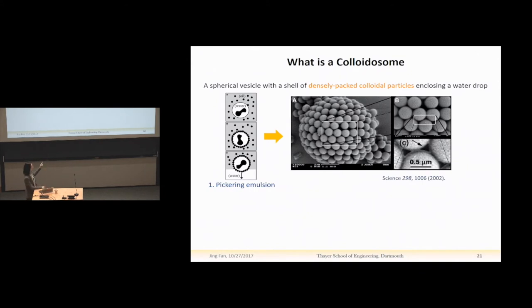But the difference between the Pickering emulsion and the colloidosome is that the Pickering emulsion is a water drop in an oil. But for a colloidosome, both the inner phase of the vesicle and the continuous phase are water-based. And actually, the first colloidosome was developed by fabricating a Pickering emulsion first, and then transferring these water drops from oil to water.